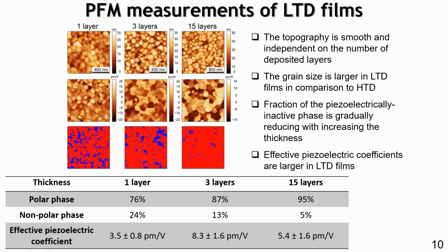And in the 15 layer films, we have about 95% of the piezoelectrically active phase, and this makes sense. So it's more or less a single phase, and probably the 5% can also be attributed to the contribution of the grain boundaries or something like that.